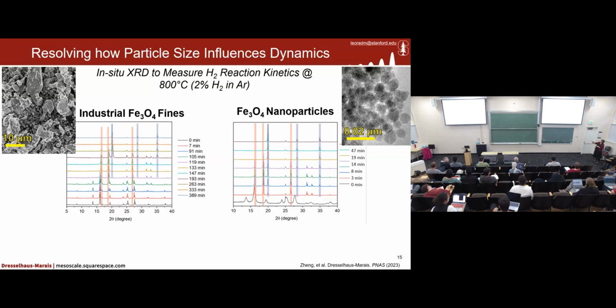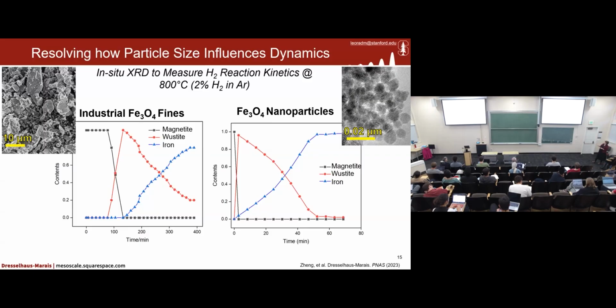And we discovered very quickly that there are these tiny, tiny nanoparticles that we know very well should not react the same way as normal bulk materials. So we decided to look specifically at just those nanoparticles to understand how the nano behavior, the nanochemistry, would alter the progression of this well-studied reduction reaction. So we did some X-ray diffraction and were able to validate that, in fact, it's a good surrogate system to describe some of the smallest length scales in this problem.